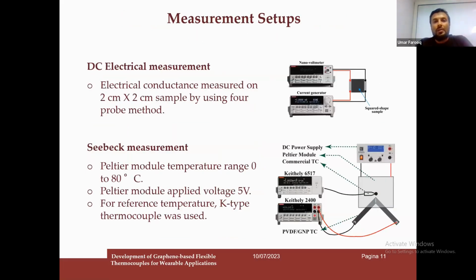After that, we took two different types of measurements: the DC electrical measurements, by taking a 2 centimeter by 2 centimeter sample and using a 4 probe method to find the conductivity of our sample, and a second setup for the Seebeck coefficient measurement of our sample. The whole setup consisted of a Peltier module which can produce a temperature range from 0 to 80 centigrade, the applied voltage was 5 volt, and for the reference signal we took a K-type thermocouple sensor for taking the reference temperature which we were applying through the Peltier module.